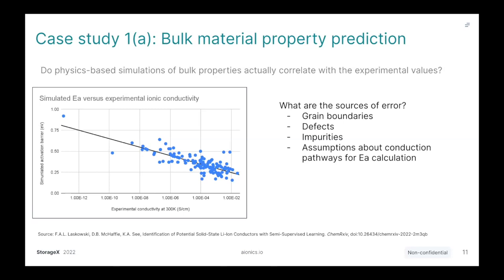and then also computes a simulated activation barrier for ion diffusion. It's like an EA versus conductivity plot. We would expect these things to be correlated, in that the conductivity goes with the exponential of the activation barrier. This is a Boltzmann process here. And so this paper has pulled these data for hundreds of data points. And as I mentioned, it's a great source. I just pulled a few here to look at what the emerging trend is.